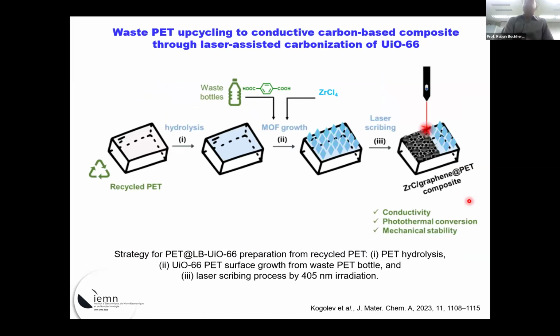I will go to another example where we wanted to combine plastic recycling with hybrid materials. So we took plastic. This is just PET, the plastic bottles, you know. And what we did here, we hydrolyzed this chemically. When you hydrolyze the PET bottle, you generate this molecule, which can then be combined with any metal salt. Here we use a zirconium salt, but it could be any metal salt, and then you can grow MOFs, metal organic frameworks, on the plastic.